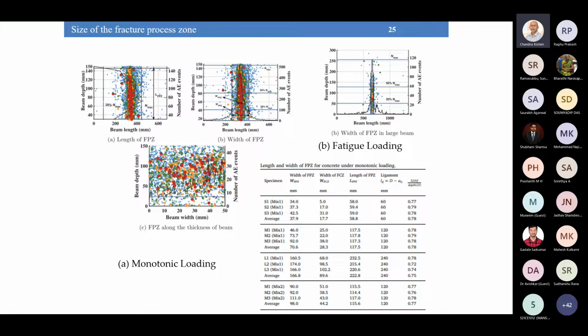But for fatigue loading, we don't see this. We see only a very localized, narrow zone of only low energy acoustic emission events. So we can't use this method to compute the size of the fracture process zone. So what it means is, is there really a fracture process zone under fatigue loading? That is a question which we had.